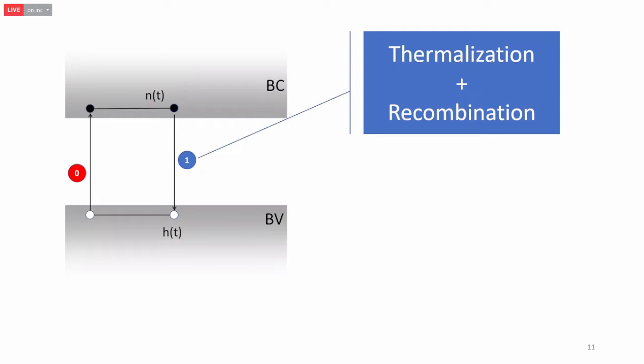We have two main processes, that is exciting, generating the electron-hole pairs. And then these have probabilities, basically experimental probabilities, that depend on the radiation pumping that you're using. And then there is a process here that involves both thermalization and recombination that gives the energy out of the primary process that is creating the electron-hole pairs. This will be characterized in our model by alpha, and the typical times here can range from 10 to the minus 5 to 10 to the 1 nanoseconds in a typical scintillator.